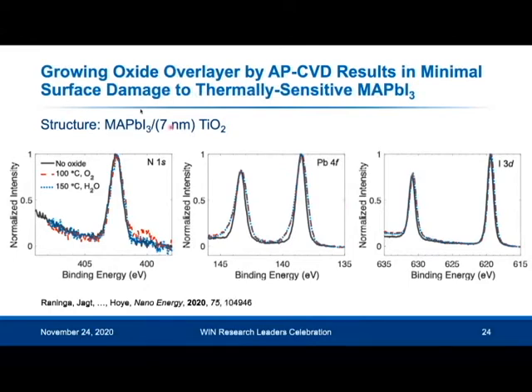So we looked at the buried perovskite interface using XPS. So the nitrogen core peak comes from the methylammonium, the lead and the iodide comes from the inorganic sublattice of the perovskite. And you can see that after growing the TiO2 under mild conditions, we do see this small peak appearing here around 400 electron volts core level binding energy. And this is from degradation products.